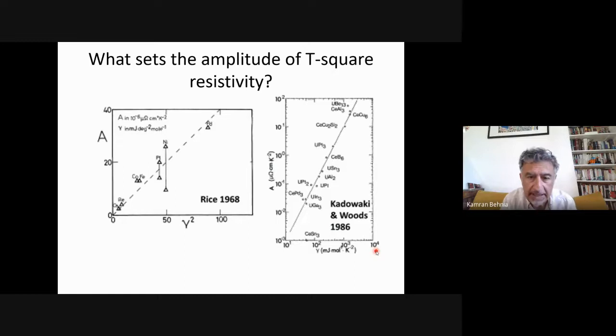In 1968, Rice plotted this figure. He took the T-square resistivity of several elements. Here you see osmium, rhenium, cobalt, iron, platinum, nickel, palladium as a function of gamma square. And he found that this A, the prefactor of T-square resistivity, scales with the square of gamma, which is the T-linear electronic specific heat.